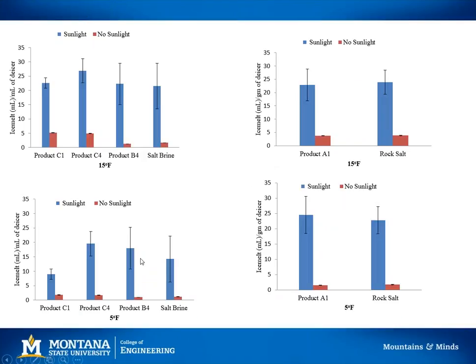And here's the data. So for these 3 products and the salt brine control, we measured ice melt at 15 and 5 degrees. And one major thing that you can see from this data is that regardless of product type, UV light adds to melting capacity. It significantly increases it. So we also measured the ice melting capacity with no lights on and no UV exposure. And you can see here that there is ice melting occurring, but the ice melting rates are much lower than with the direct UV exposure.